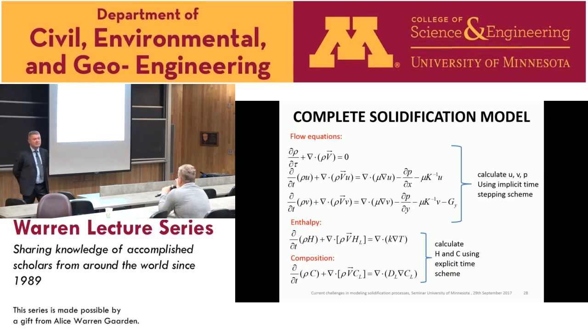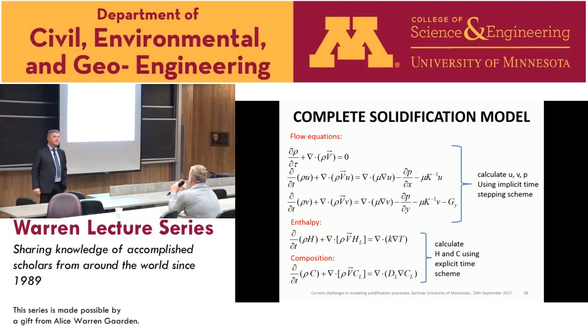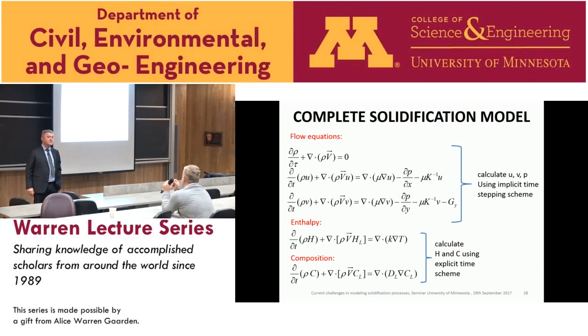Well, okay, let's say that you use some turbulence closure like the K-epsilon model. But if you consider the diffusive interface between the two phases, you assume a certain smooth function that will make a continuity between the two temperatures. But in a turbulent flow, eddies of different frequency and intensity will approach that interface and move away from the interface. They will continue renewing the diffusive sublayer at the interface. So in that case, that function will change in time. It may change shape, it may change width. So how would you take into account this change in the diffusive layer in space and time if you have a turbulent flow?